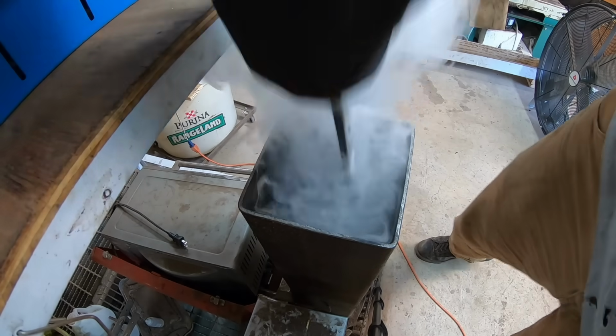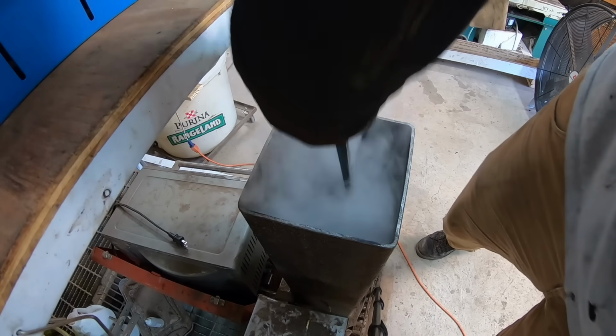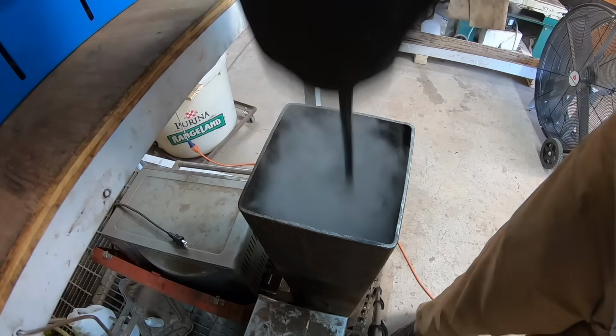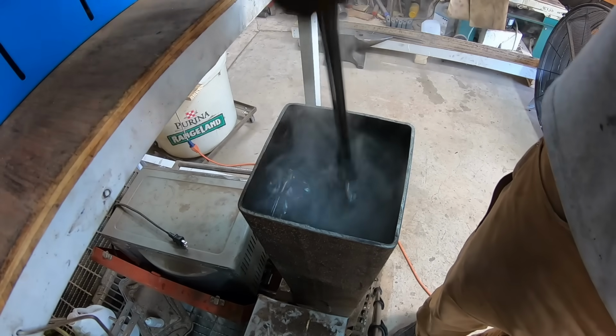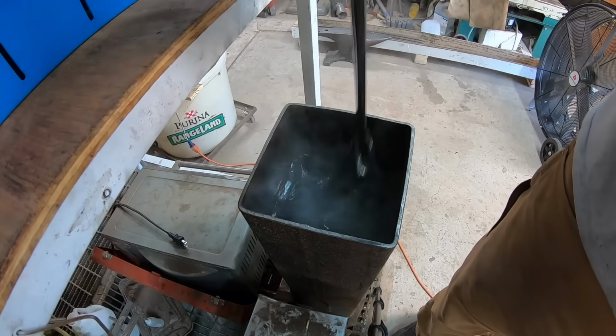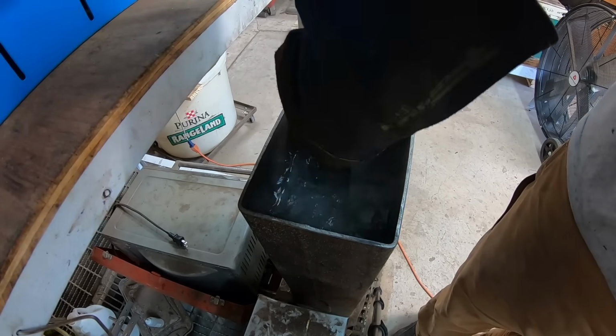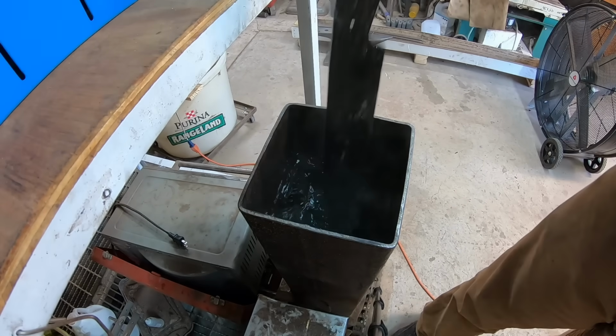I did a couple of thermal cycles in between before quenching, and here's the quench. This is a pretty heavy blade, so we've got to make sure that the residual heat is out of there so we don't get any over auto tempering on this blade here.